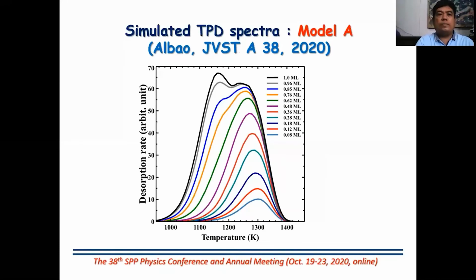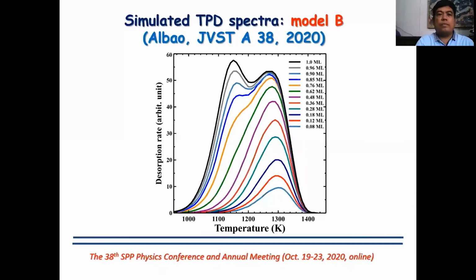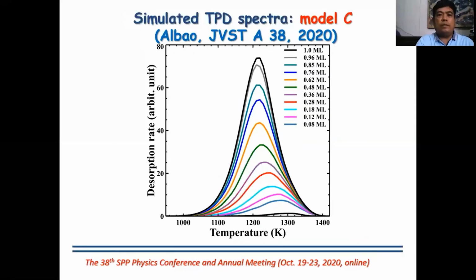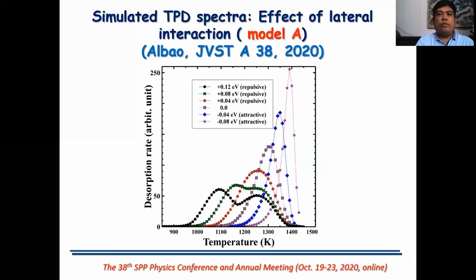Model A, Model B, Model C. Note that of the three, Model A best resembles the features of the experimentally obtained TPD spectra shown earlier. Although Model B, the one where minimal dimerization is allowed, is also a good match to the experiment, though the secondary peak is taller than the primary peak, contrary to experiment.